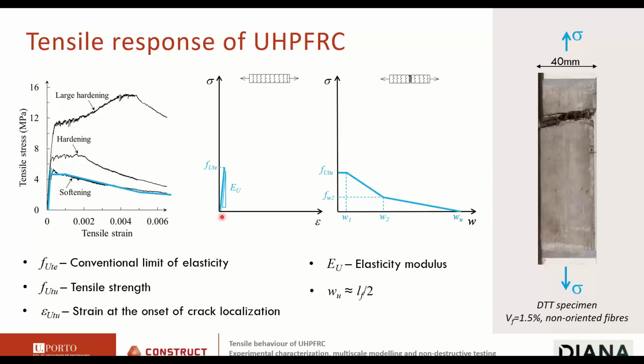So in this case, we need a linear elastic branch up to the peak stress and then a stress versus crack opening relation for the post-peak part of the tensile response. So in this case, the post-cracking tensile strength is smaller than the conventional limit of elasticity.